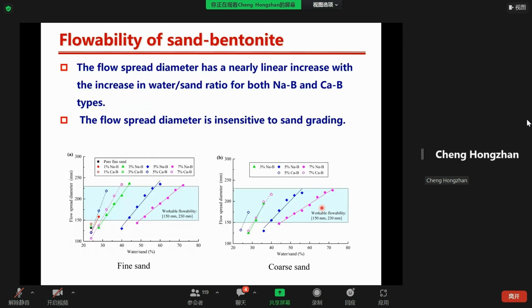Okay, next are our results. First, the flowability result is provided. The desired flow spread diameter for construction purposes is between 150 and 230 millimeters, as shown in the picture. From the next picture, we can see that the diameter for the pure fine sand is below 150 millimeters. It means the addition of bentonite is required to obtain the desired flowability.